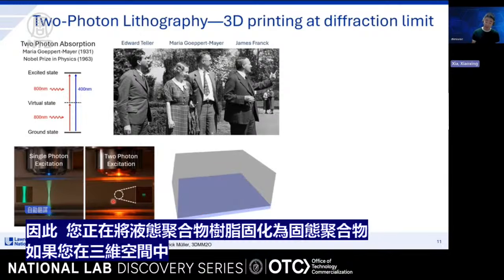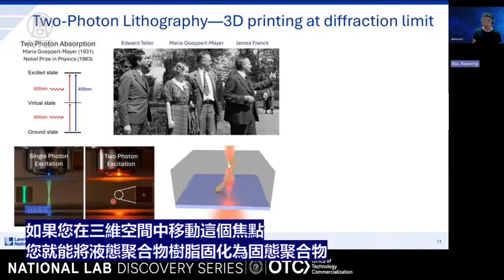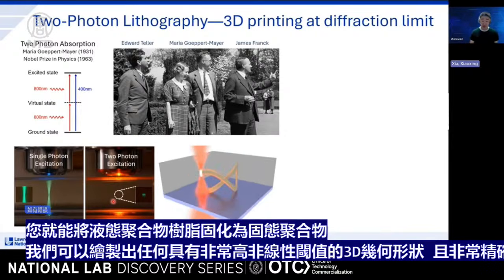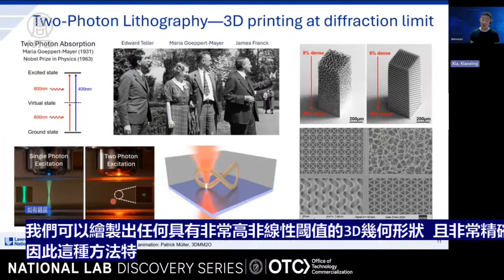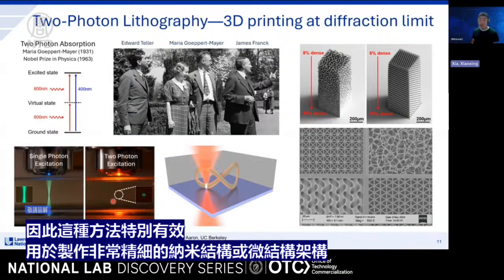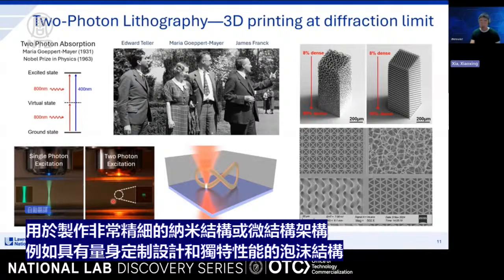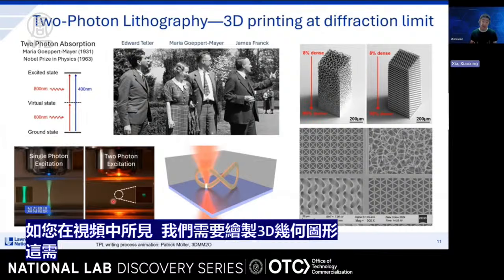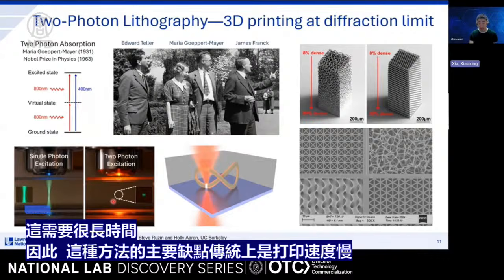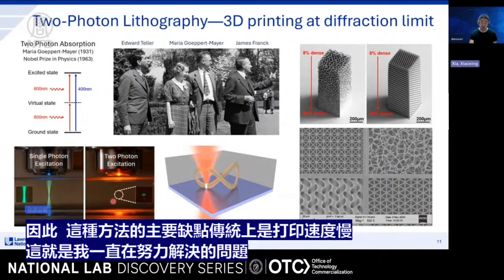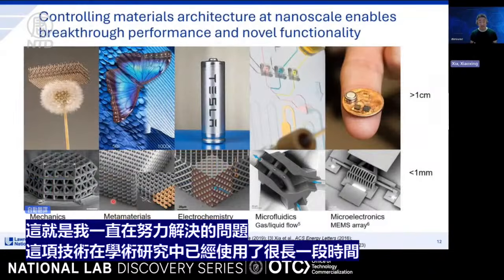So if you move this spot in 3D, we can draw out any 3D geometry with a very high nonlinear threshold that is very accurate. So this method is particularly good for making very fine nanostructure or microstructure architecture, such as foam structures with tailored design and bespoke properties. And as you can see in the video, we have a very fine pen tip, and we need to draw out 3D geometry, and it takes a very long time. So the key drawback of this method traditionally is the slow printing speed, and this is what we have been working on to solve.